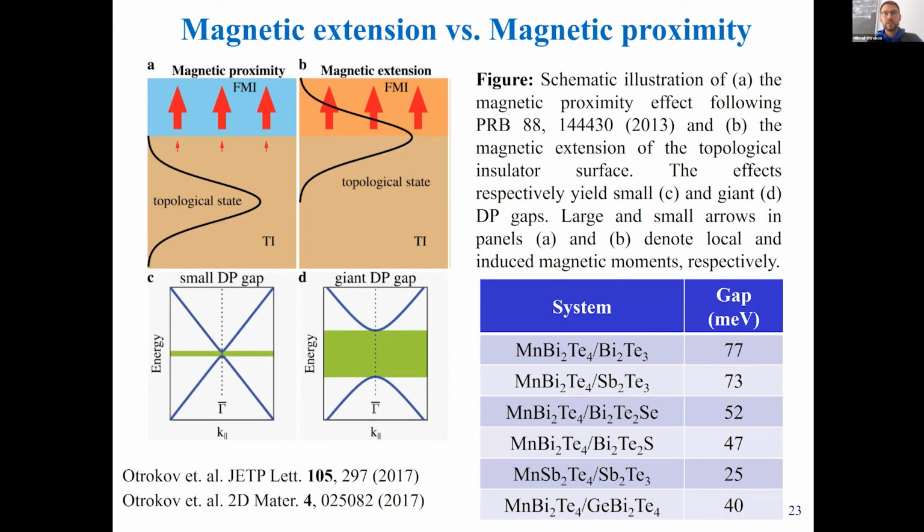It is interesting to compare this approach to the, okay, I have one more question. What kind of DFT calculation can be used to predict a bandgap of 77? Yeah, well, in this case, this was a VASP calculation, projected augmented wave method, but I believe you can reproduce it with, let's say, FLAPW or other methods. For example, another pseudopotential method would be the SIESTA code. So I don't think it really depends on the, sorry, it was about the functional, yeah. That was GGA plus U.